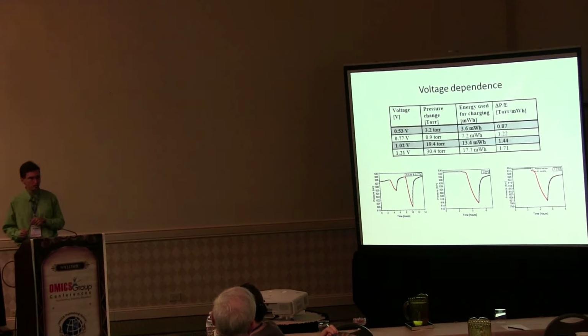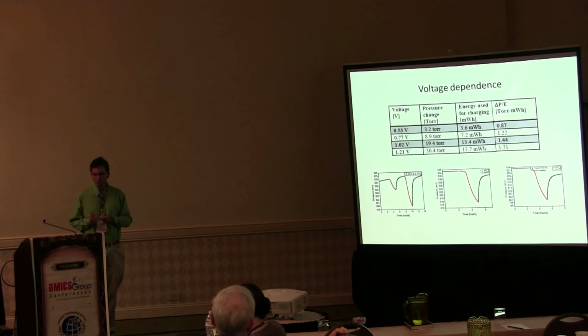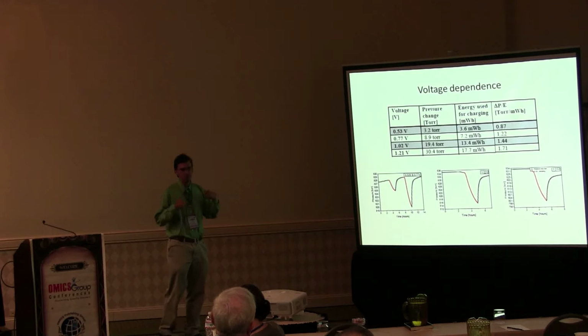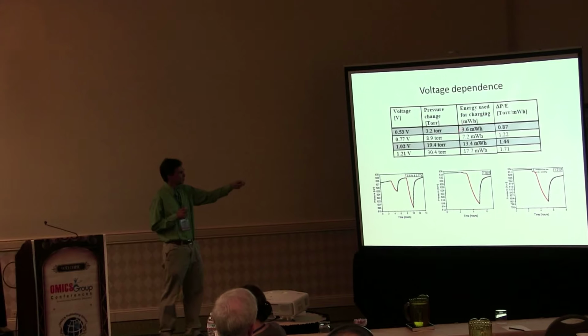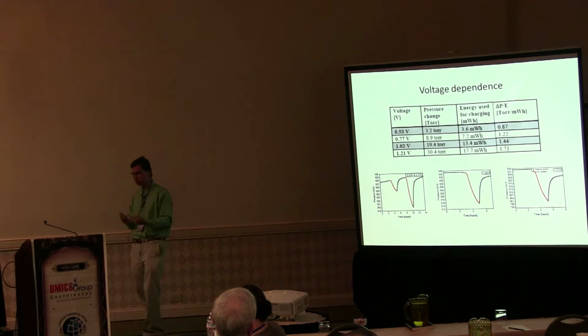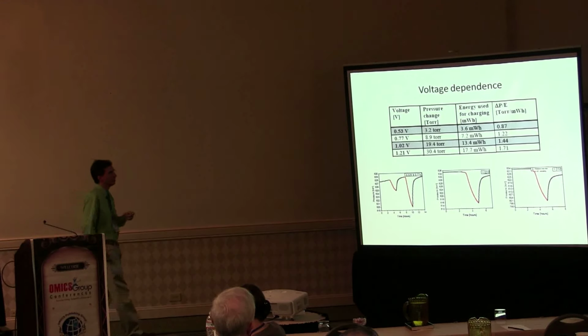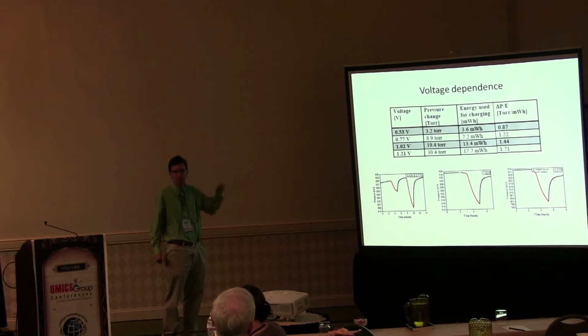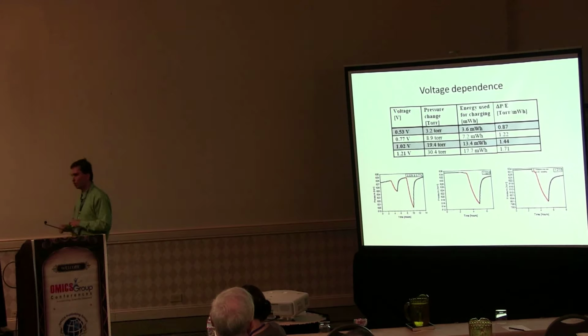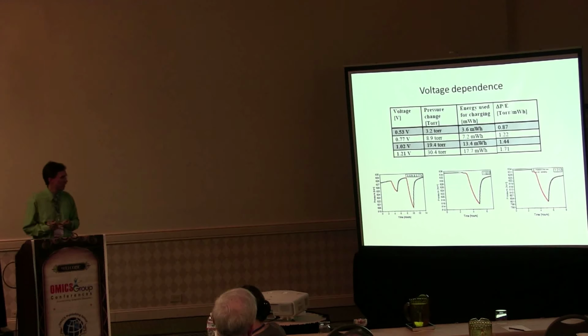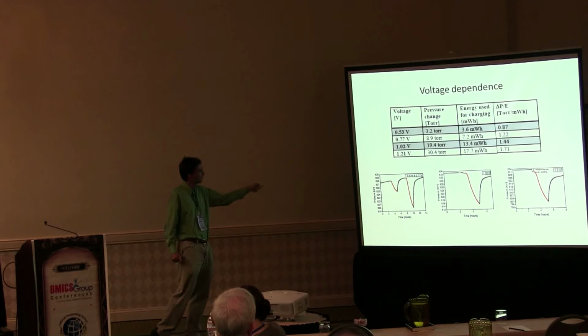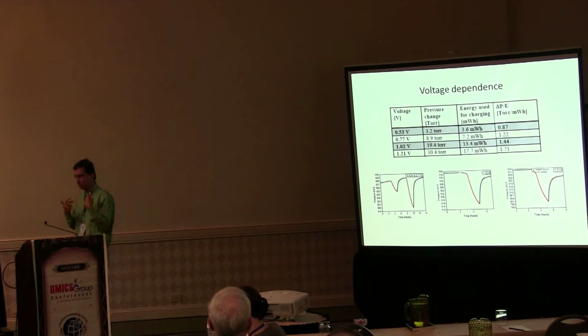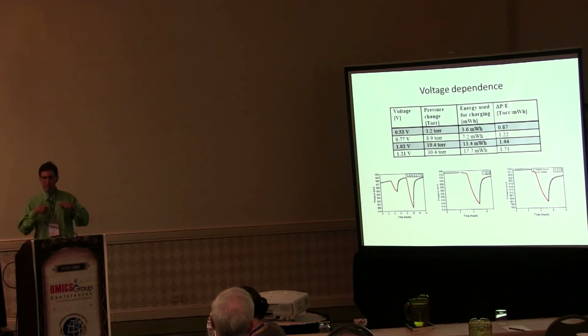In addition, we were interested in the question: how much energy do we use during such an adsorption half cycle? You see that here. There is a significant increase of energy that we use during the charging of the capacitor. However, when you look at the ratio ΔP over E, the pressure change over energy, this ratio also increases. That indicates that we are operating more energy efficiently at a higher voltage. Unfortunately, we cannot go higher than 1.2 volts in aqueous electrolyte systems, because otherwise you get electrolysis. However, with organic electrolyte systems, you may be able to go to significantly higher voltages, up to approximately 5 volts.